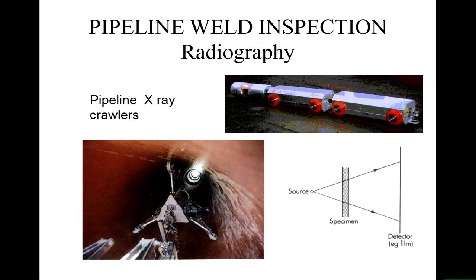So a couple of internal sources. The sources act like point sources. So here's your pipe specimen, there's the source, and you get this cone, and then on the detector you expand things a little bit. As we've drawn it there, the detector is a long way away from the specimen, but often we put the specimen as close to the detector as we can, so that we can get a more realistic measurement of size. So if you want to use this technique to measure the size of defects, you have to calibrate for the distance between the film and the material that you're measuring. That's something that you need to be aware of.